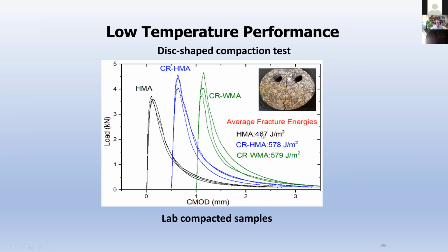So the first one, for the hot mix asphalt, is 467 joules per square meter, and for the two rubber materials it is 578 and 579. What that really means for this case, which was for a Keweenaw County project we did, is that you can see you have some bump in the fracture energy. That really means this material will perform very well in cold climate, or not easily get cracked. So that is one of the things I really like to show here.